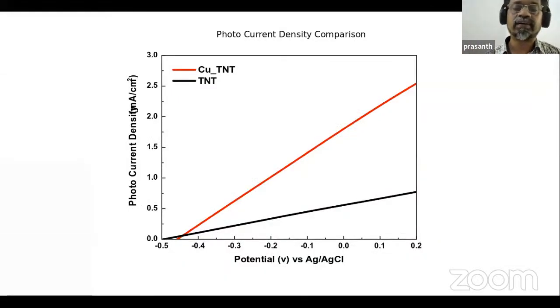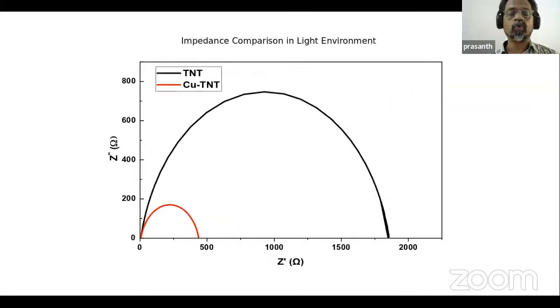And then we can study the photocurrent behavior of the system. After copper doping, you can see a good improvement in the photocurrent density of the material and also the impedance. If you study the impedance behavior of the system, you can see a considerable reduction. That is the most important part of the study. The impedance of the electrode is considerably reduced by incorporating such doping. So that is one element.